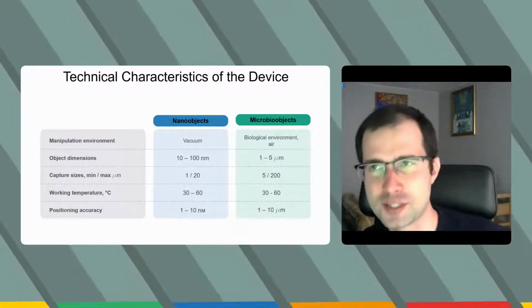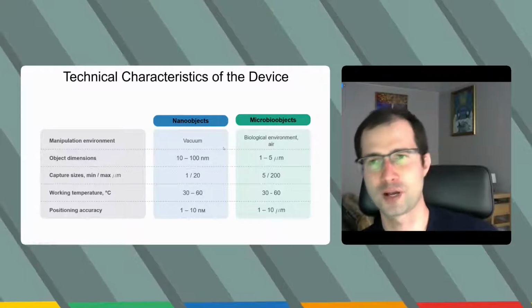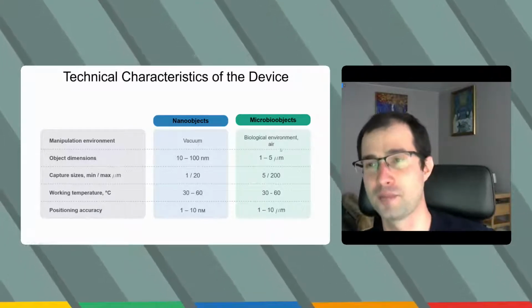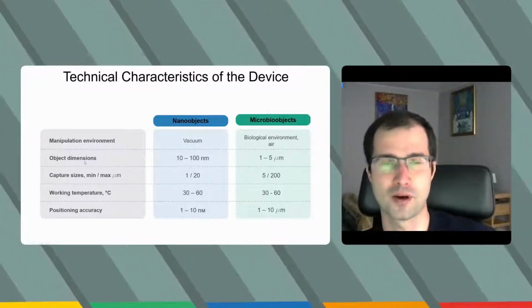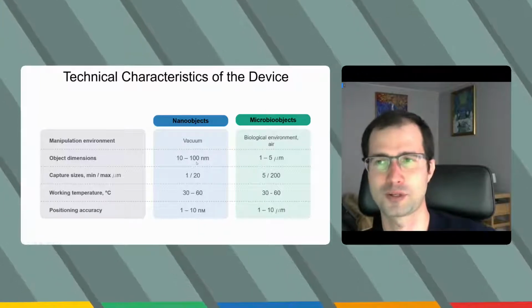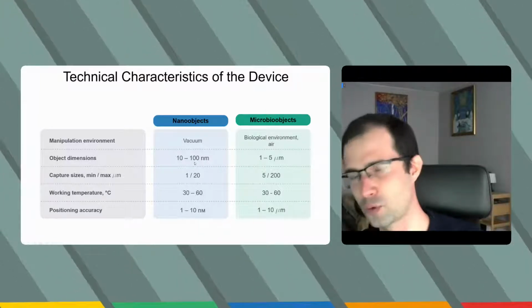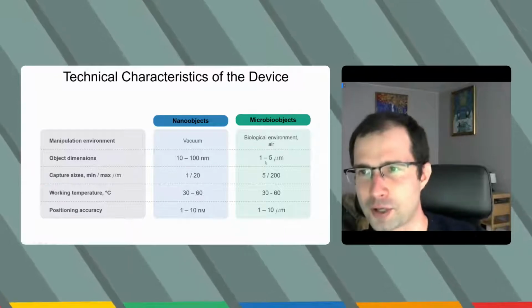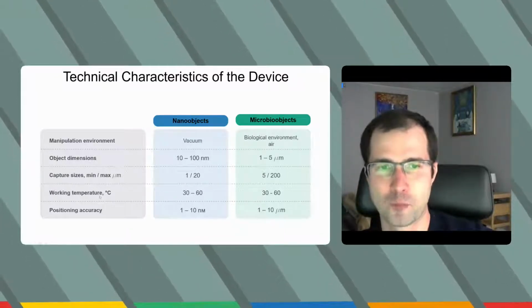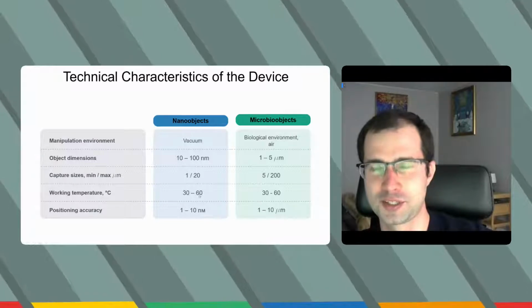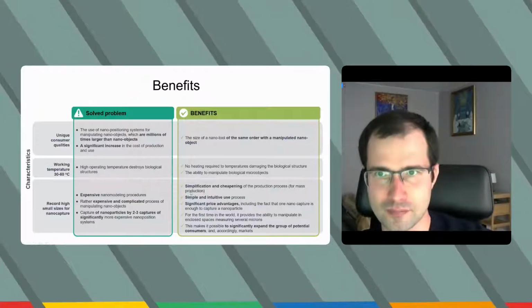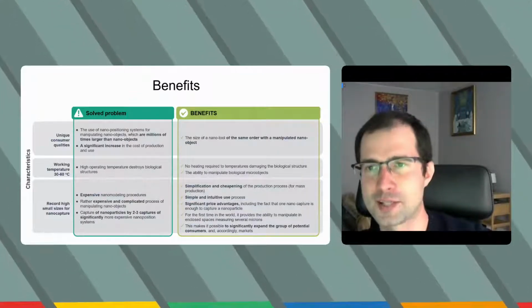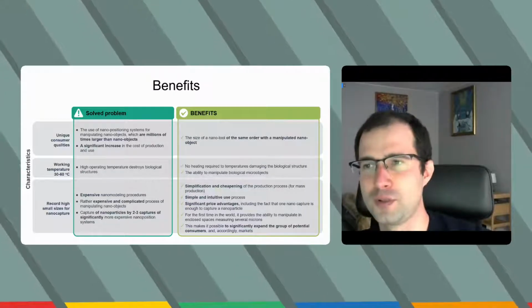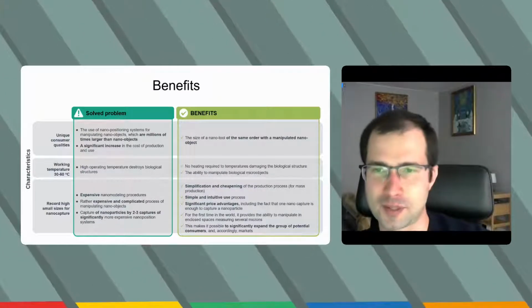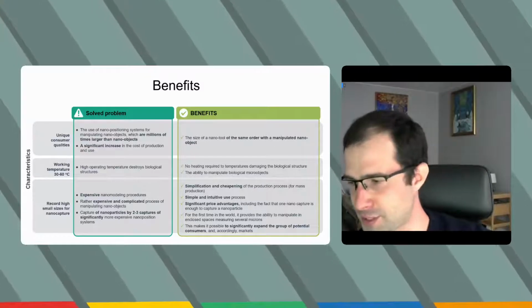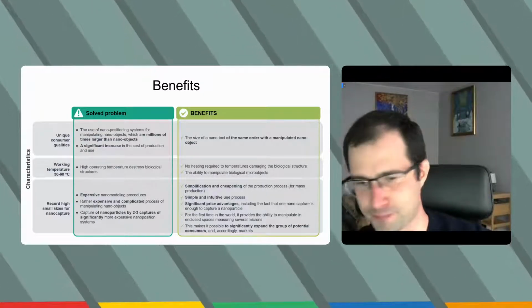The technical characteristics of the device are as follows. The manipulation environment can be vacuum chamber or air. Object dimensions are from 10 nanometers to 100 nanometers, and you can also manipulate micron objects. Working temperature is from 30 degrees centigrade to 60 degrees. The size of the nanotool is of the same order as the manipulated object. This is the benefit of the shape memory effect nanotweezers.